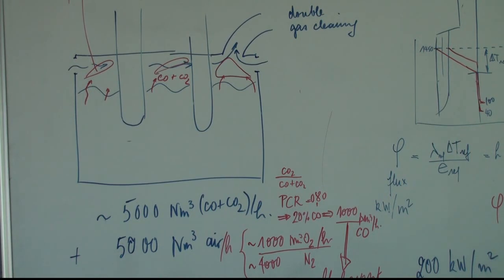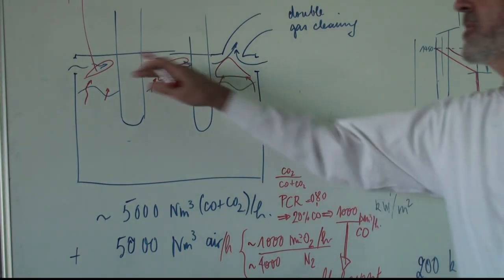I tell you, this is real life. Things like that I have measured in the Colwood furnace when we were not tight, because we also had a water-cooled roof, and on a water-cooled roof you measure the temperature of water in and water out, and you can calculate. What is the result? It's easy. Thousand cubic meter CO, delivering each 3.5 kilowatt hour, is 3,500 kilowatt, and that is 3.5 megawatt. That's a huge burner, I tell you. That is heating up your roof.